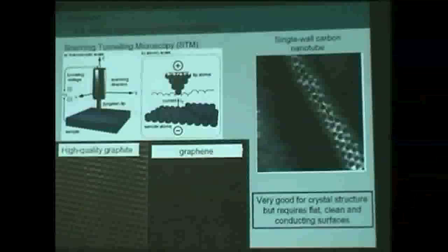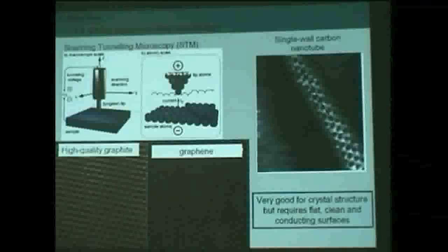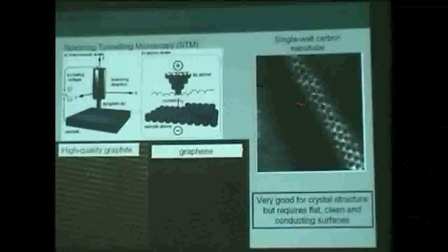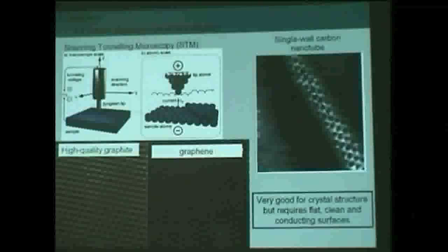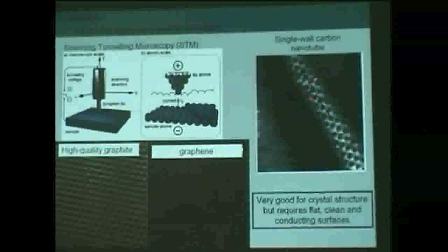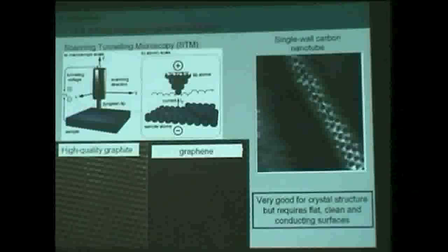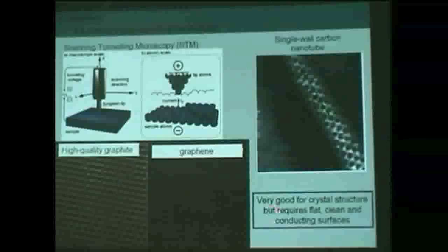This kind of characterization confirms that it's a hexagonal lattice and that there is a chiral angle, which is not always 0 or 30. This technique can also give you the diameter of the tube if you have a careful preparation. So this technique is very good for getting the crystal structure and seeing atomic details, but it requires very special conditions, like a very flat surface.